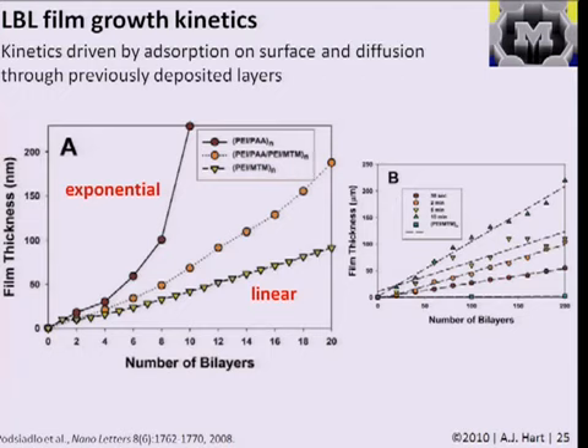So that means the more layers you have under the surface, the more of this interdiffusion and swelling of previous layers you get. So that indeed leads to an exponential dependence of the thickness on the number of bilayers in certain situations. However, once you reach a saturation state, where the thickness of the film is greater than the penetration depth of this diffusion process into the existing material, then the kinetic becomes linear, but becomes linear based on having adsorption and diffusion.